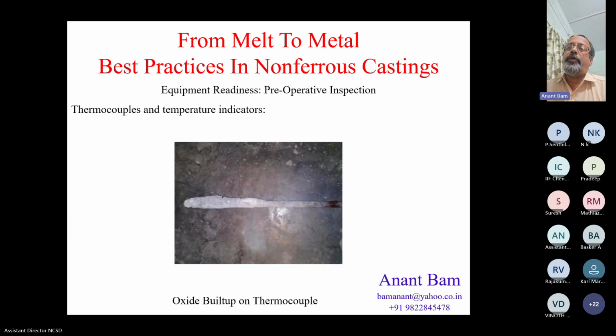Here is a photograph of a dip type thermocouple having a very large deposit of oxide on it. And again, as I told, these oxides keep on dissolving into the metal, thereby making the metal dirty. Again, it's a bad conductor of heat. So the reading which is taken by the thermocouple is a false reading. The metal might be quite hotter than the reading shown by such a thermocouple. Next slide, please.